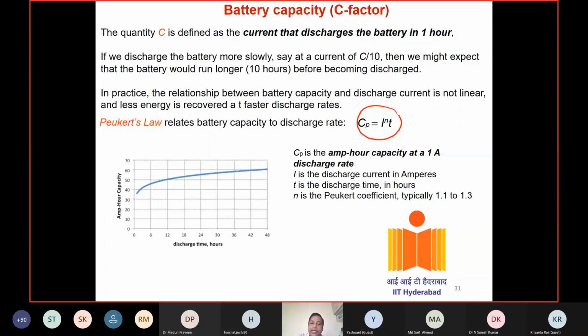I'll come to that. In general, for a lithium-ion cell, if it is a 1 ampere hour cell, that means it is 1C rate. 1C rate is the capacity in 1 hour. That means you are passing 1 amp current, and C by 10 means you may be passing 0.1 amp current. Correct? 5C rate is 5 times of this. But a lead acid cell doesn't follow the same trend.